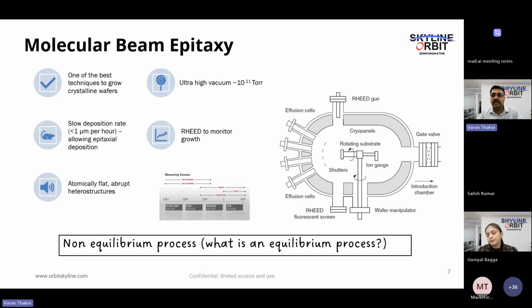Apart from that, we have different ways to see what is going on in the chamber. For example, there are several gauges which measure the pressure, and growth is measured using RHEED. RHEED is a very typical instrument that is used. The full form is reflection high energy electron diffraction. Basically, an electron beam strikes the substrate and falls onto a screen, creating a diffraction pattern. Based on this, we can understand the crystal structure of the overgrown film, right? The heart of the MBE is its pumps, which give it the vacuum.